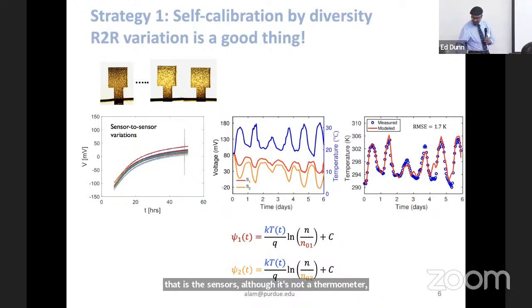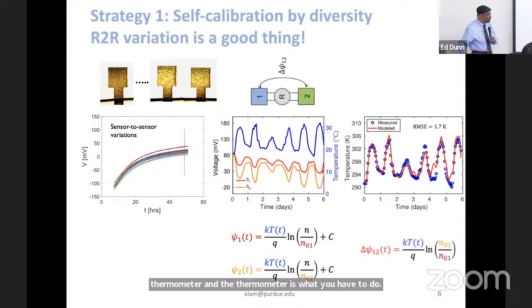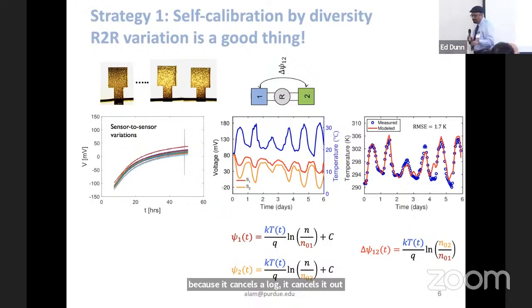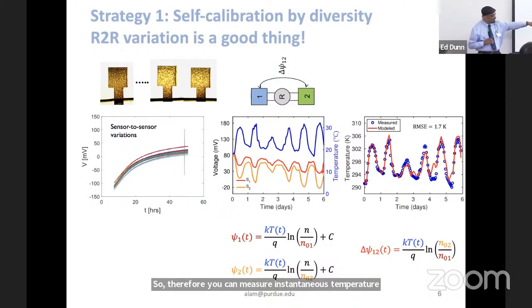And the thermometer is what you have to do. Instead of having one sensor, you have to have two. And when you have two, the differential voltage between them, because it's a log, cancels it out. So therefore, you can measure instantaneous temperature, morning to afternoon, summer to winter, any variation in the temperature by measuring the difference in the voltages, by using the natural variation of the thickness of the sensors in the roll-to-roll process.